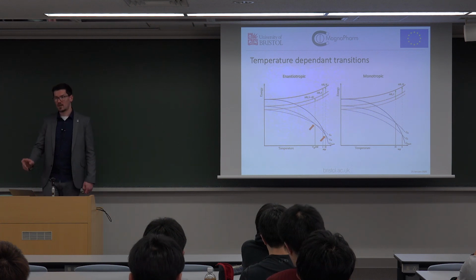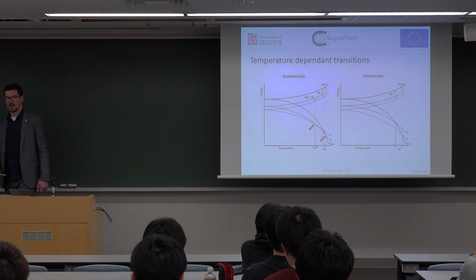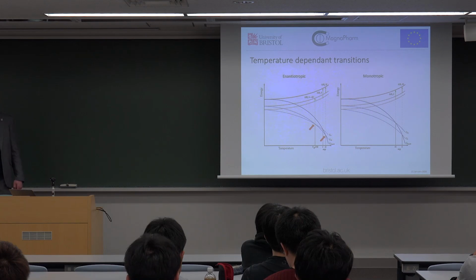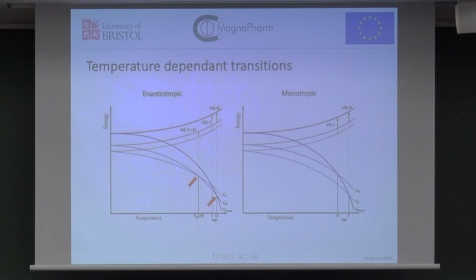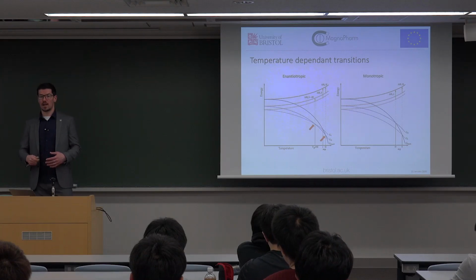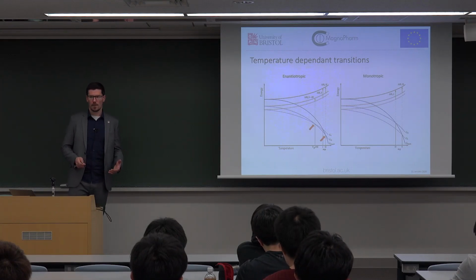One other point about enantiotropic and monotropic crystal systems. With polymorphs, you can have different phases appear at different temperatures. So if you cool down pyrene, it's a small 4-ring system. If you cool it down at about 100 Kelvin, the whole system changes to a different polymorph, and then you warm it up again and it changes back to where it was originally. Now that's called an enantiotropic transition.